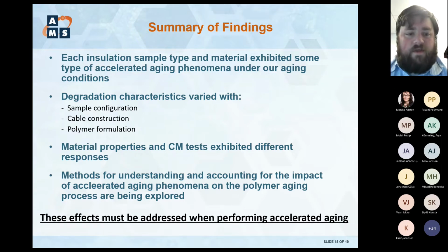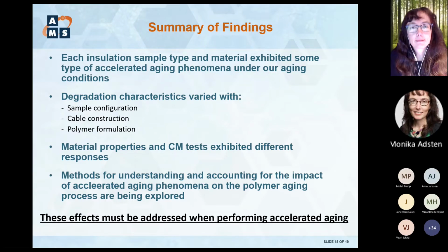And we've also looked into methods for understanding and accounting for the implications and the impact of aging phenomena on polymer properties, using profiling and material evaluations, and relating one set of data to another. It is important to know that these types of things must be addressed, or at least understood, during an accelerated aging program. Otherwise, you're going to get data that is very hard to interpret, especially for electrical measurements, which can be very impacted by these types of things when you're trying to measure something that's highly affected by aging phenomena.